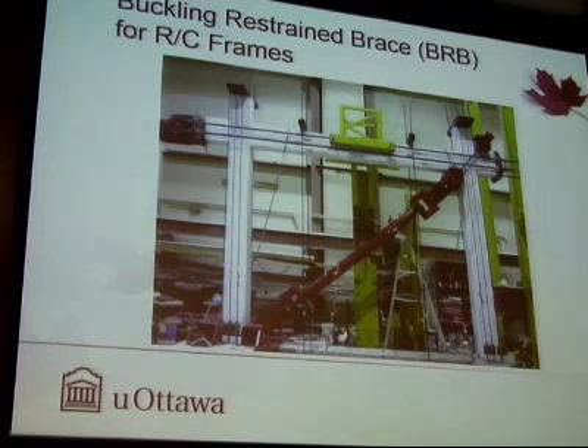And we are currently in the process of developing buckling restrained elements, BRBs, braces for reinforced concrete. Unlike the typical BRBs that are used in industry, which consist of various size steel plates, we're looking at using bars. These are high-strength bars, and they are shaved inside the pipe to encourage the bar to yield in that region so that there will be controlled yielding. However, they're not allowed to buckle because of the exterior constraint provided by the pipe.